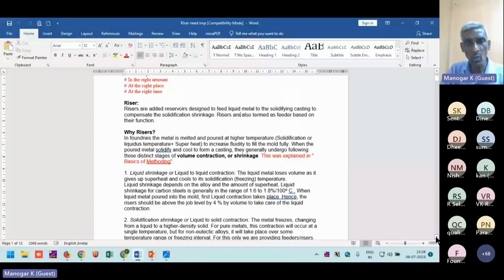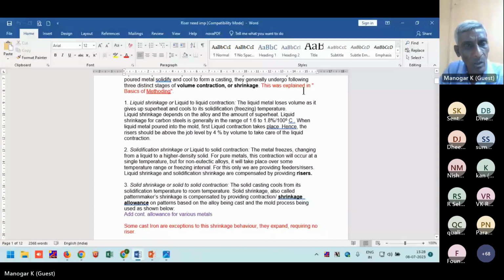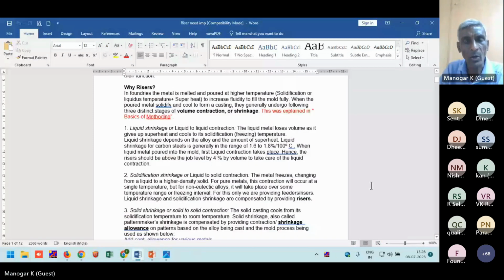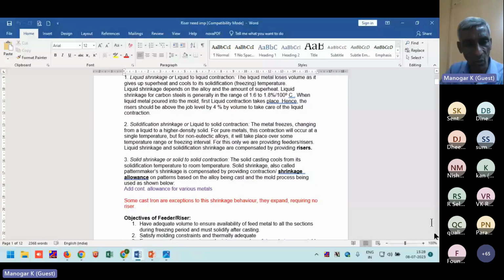The risers, anyway, we have discussed. So why do we use the risers? If the metal is melted and poured at high temperature, solidification happens at liquidus temperature plus superheat to increase the fluidity. The poured metal solidifies and cools to form a casting. They generally undergo the following 3 distinct stages of volume contraction. One is liquid shrinkage, that is taken care of by riser height, extra height, and the solidification shrinkage, that is liquid to solid contraction. For this, we are keeping the risers. So that's why we have discussed so far how to calculate the riser. And the solid contraction is taken care of by the shrinkage allowances in the patterns.